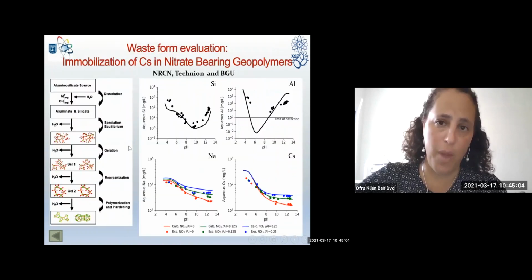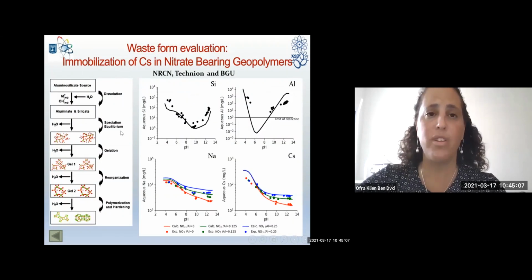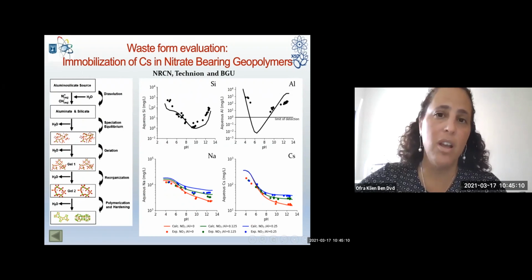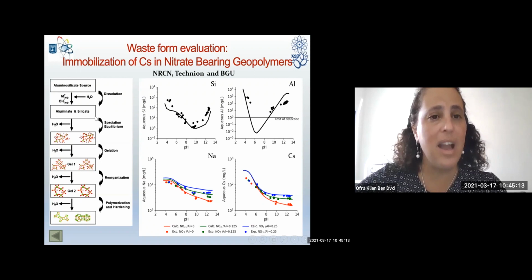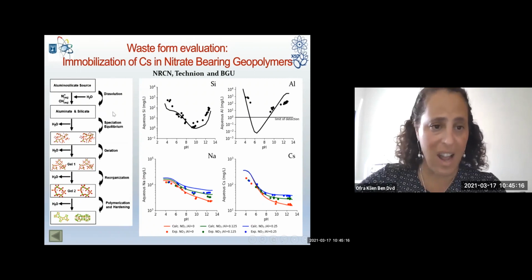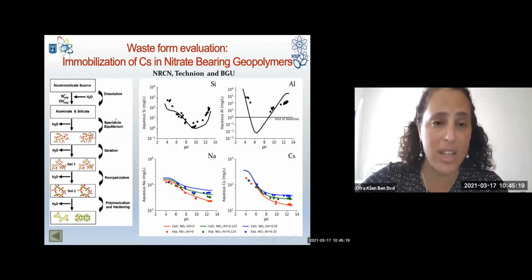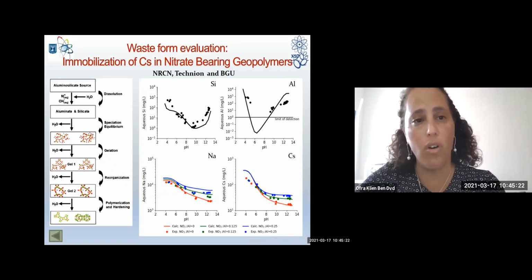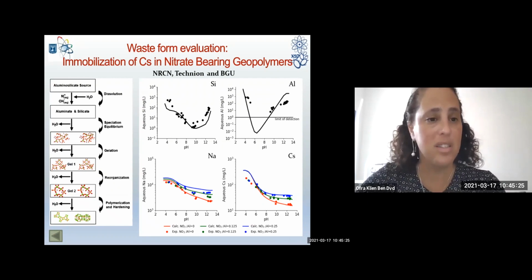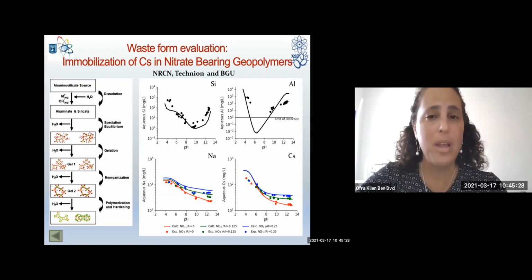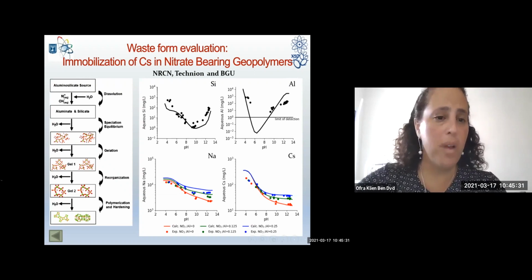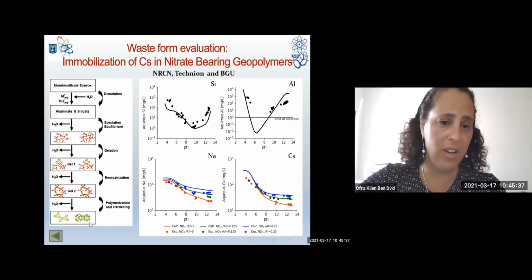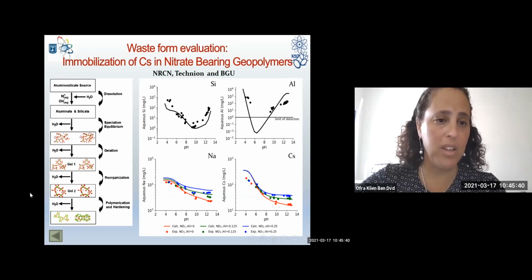Another work that we are conducting is on a different type of retention material that is called geopolymers. Geopolymers are basically silica aluminate matrices, similar to zeolites, and we make them from a mixture of an amorphous silica alumina source, such as metakaolin or fly ash, with a base. They form an amorphous, polymer-like inorganic material that has a good retention ability and a longevity, a longer time span than cements.